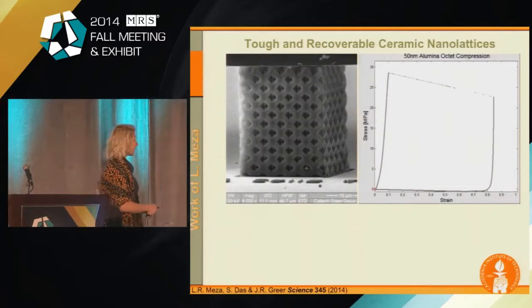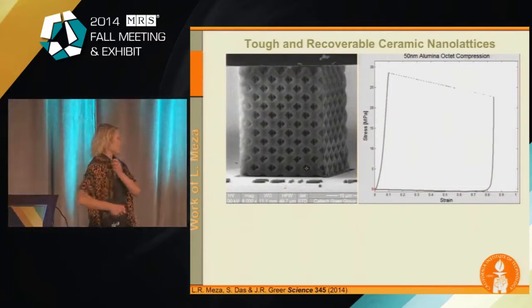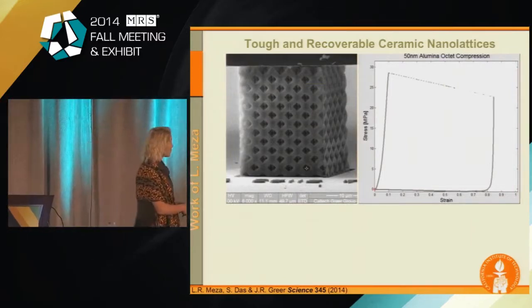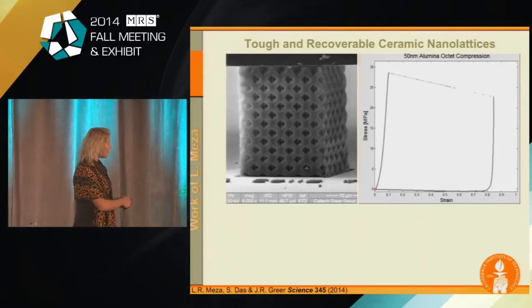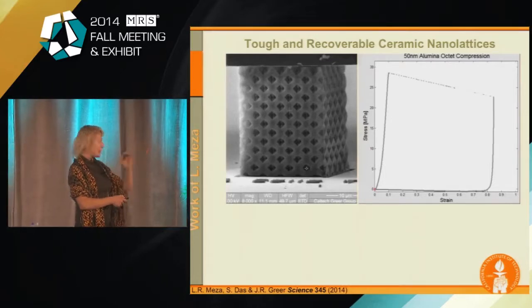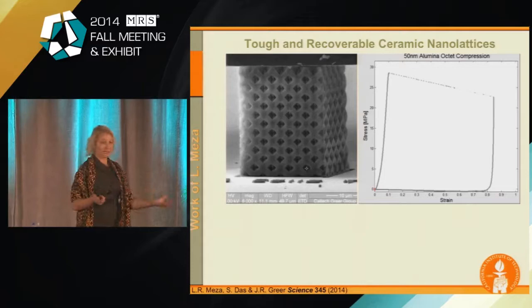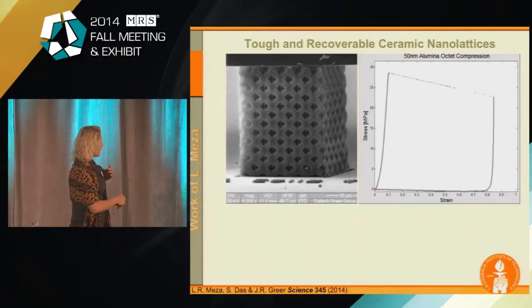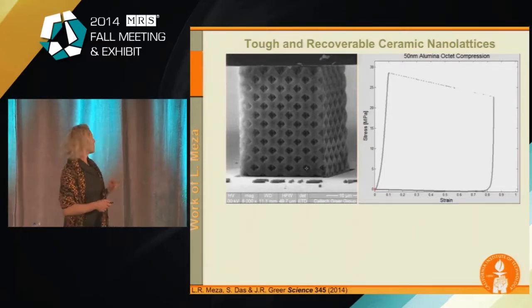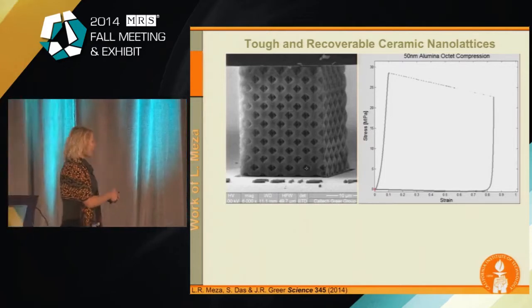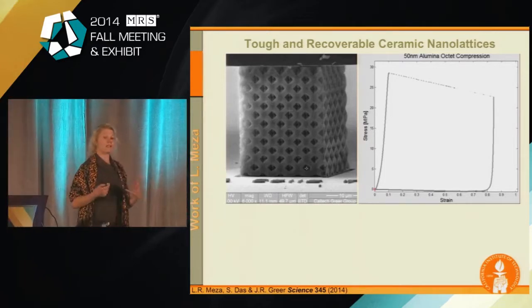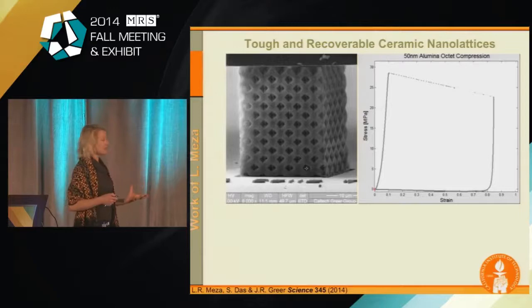So what this is, it's a ceramic nanolattice that my student Lucas made. This is an octet geometry. These are all open, hollow beam members, and they're constructed in an octet lattice that's about 99% air, probably a little bit more than 99% air. So imagine a piece of chalk with a severe case of osteoporosis. It's very, very, very open and very porous and also very brittle. This is alumina. Alumina is a little bit like a piece of chalk.